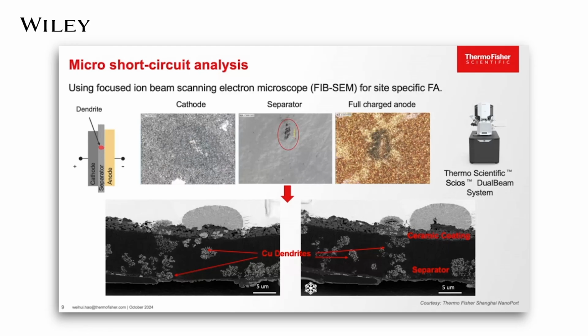After disassembling the failed battery, we often find a black spot on the anode or fully charged anode, and we need to find the corresponding location on the separator. It's always difficult for battery workers to pinpoint the defect visually or with an OM on the separator. We use SEM and dual beam to observe and locate the short circuit region precisely and decide where to cut across. Then we use the FIB of the dual beam to expose the cross-section of the dendrite inside the separator to reveal how the micro short circuit happened. Look at the image below. The bright contrast inside the separator should be the copper dendrite formed during charging and discharging.